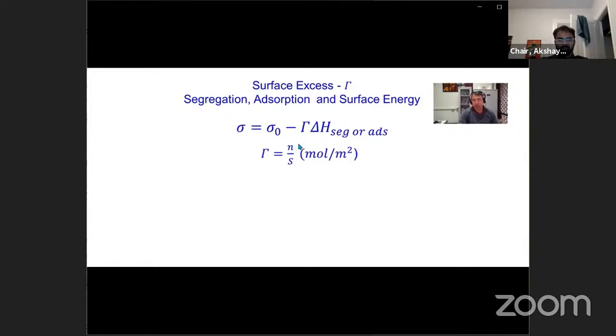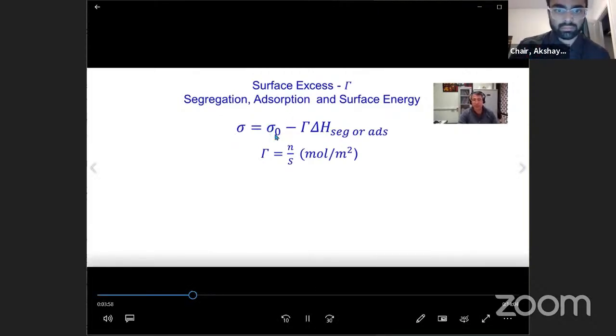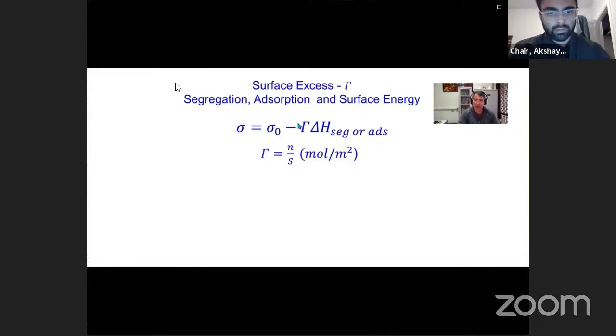And then when you have a surface excess and a rate of segregation or adsorption, the system reacts with a decrease of surface energy and then stabilization. Then the surface energy of the pure material is decreased by this amount of atoms in the surface by segregation or adsorption, and the rate of adsorption or segregation.